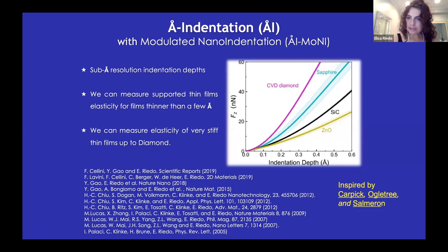The general idea is to use a modulation and to first indent in the material and then, by a very tiny sub-Angstrom modulation, withdraw the tip and then measure the change in force as a function of the change in load. And by integrating this curve, you have a force versus indentation curve that, as you can see here, gives rise to a resolution that is smaller than one Angstrom.